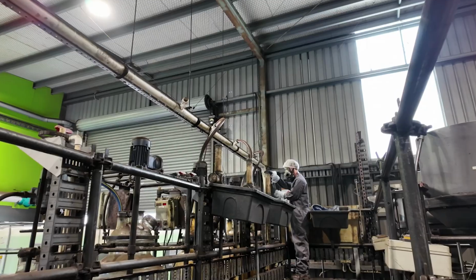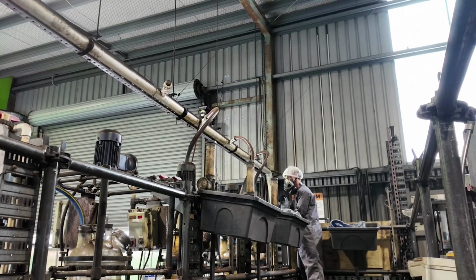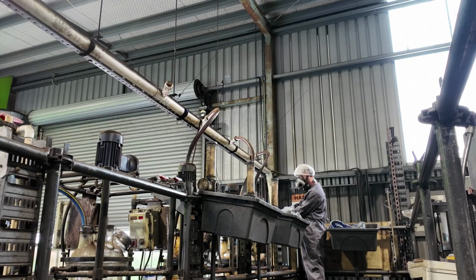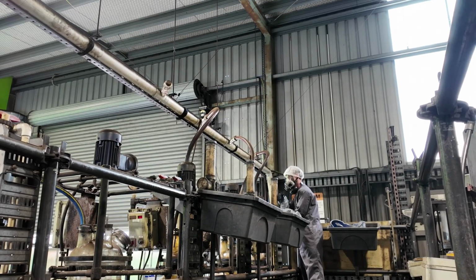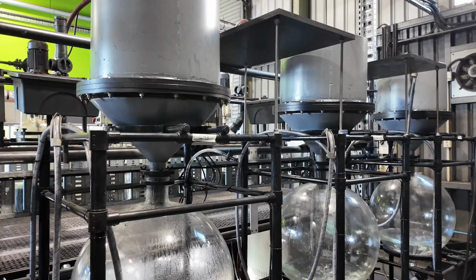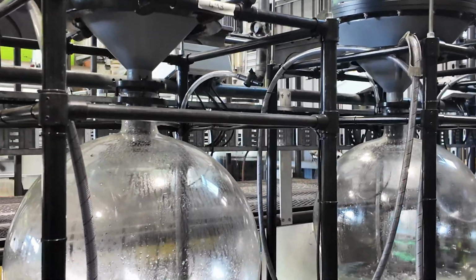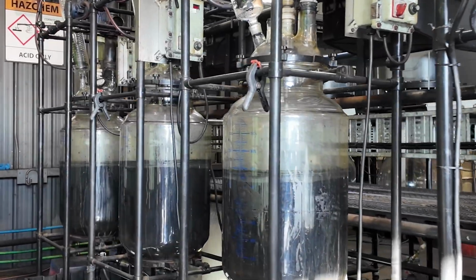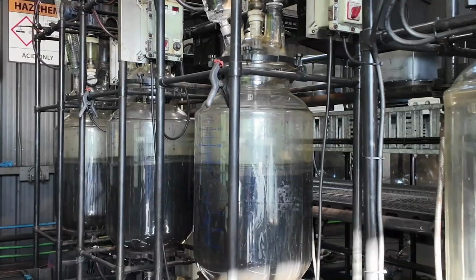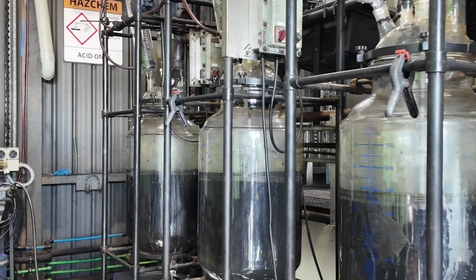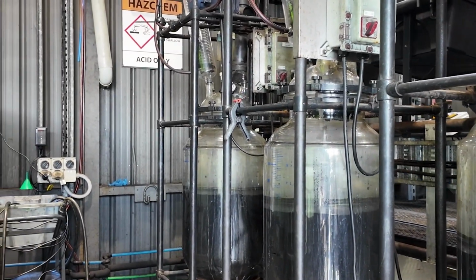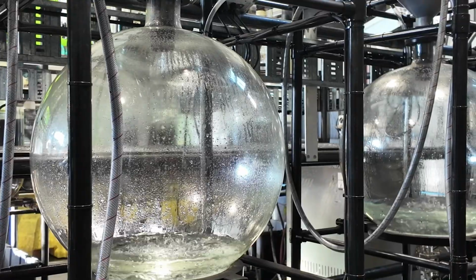The next stage is purification, removing the catalyst and reducing impurities to battery-grade levels. In this step, the graphite precursor is combined with hydrochloric acid in a carefully controlled leaching process that dissolves the catalyst and washes out the remaining impurities, ensuring the carbon is properly prepared for the downstream stages that follow.